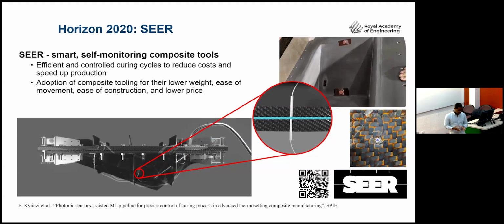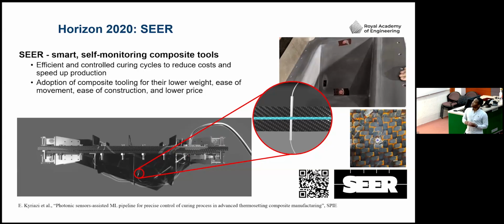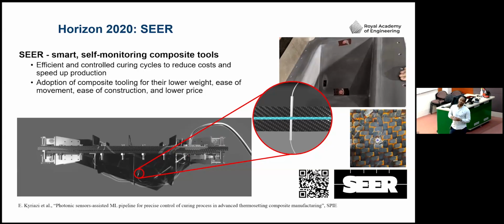So this was a project that ended at the beginning of last year, called SEER. It's just to show you why we started developing these larger through thickness reinforcing elements. This project developed, side by side, a composite tool that would self-heat and sense on the inside. In the big round picture, you have a fiber optic sensor which sits on the surface of the composite tooling. When the resin is flowing inside, it measures the refractive index to give you an idea of curing. It measures the flow rate of the resin, and of course, it measures the temperature.